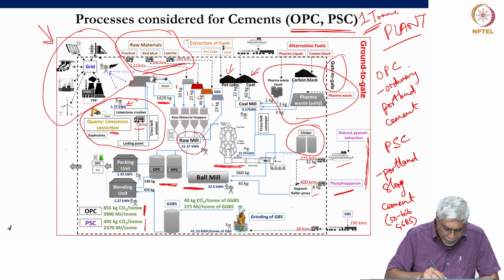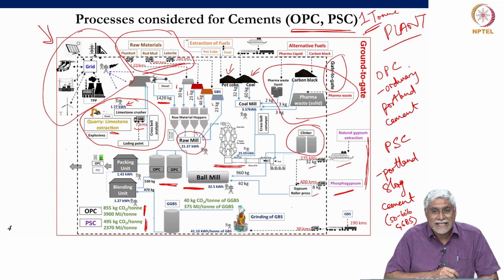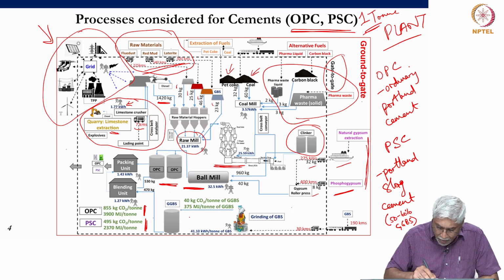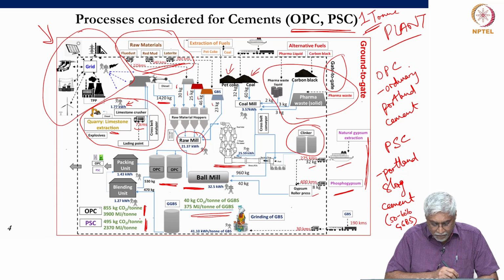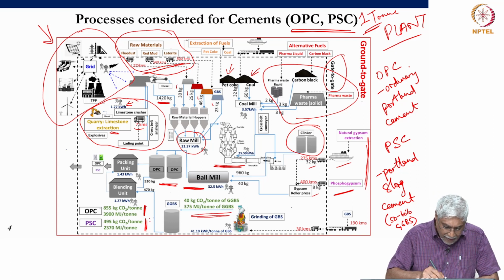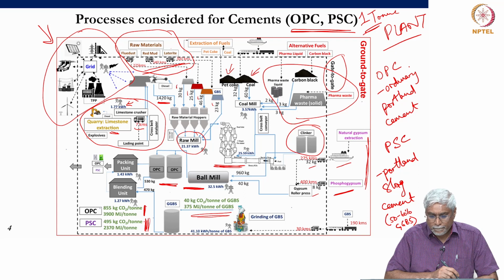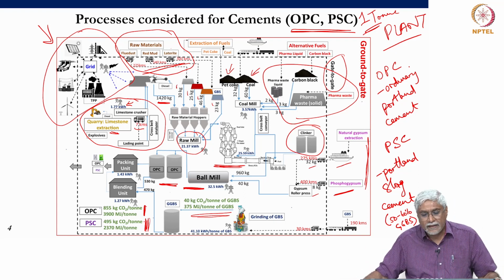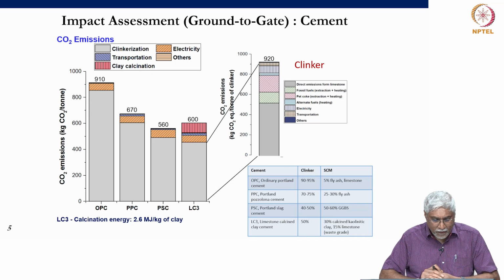The same values for Portland slag cement, where some amount of GGBS is also ground in, is about 500 kilograms of CO2 per ton of cement. Okay. So, here, as I said before, about 50 to 60% of GGBS is incorporated in Portland slag cement, and therefore, the carbon footprint and the embodied energy comes down significantly. So, this is what we will do for cement, and let me give you some examples of what we have.